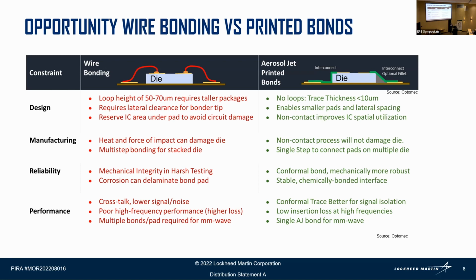Anyway, here's an opportunity that we have been working a lot on with several companies, and I think it is one of these near-term opportunities. It's getting pretty close to full implementation. This is using additive manufacturing to replace the wire bonding process. Essentially, we have this aerosol jet that sprays conductive ink, and it can form circuit traces on a circuit board. Very fine. You can probably get down to a mil in thickness. And we have demonstrated the ability to do this as a replacement for a wire bond like device. And you can see here the benefits.